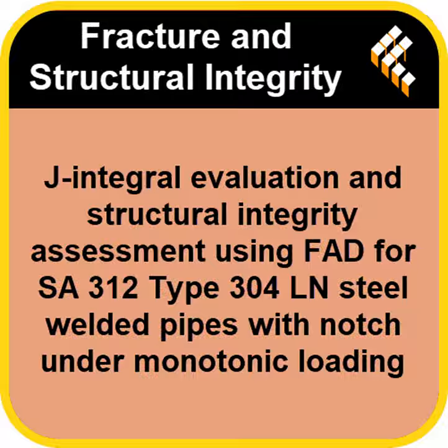What happened? Well, what's fascinating, and perhaps a bit counterintuitive, is how stable the assessment point was against the geometric variations. Variation in crack lengths and pipe thickness was found to have a negligible effect. The LR and KR values barely moved on the diagram. Really? So the structure is inherently pretty robust against minor errors in measuring its physical dimensions? It seems so for these kinds of variations. The assessment wasn't sensitive to those small geometric changes.